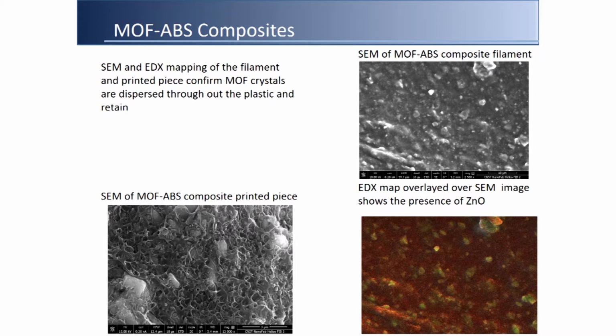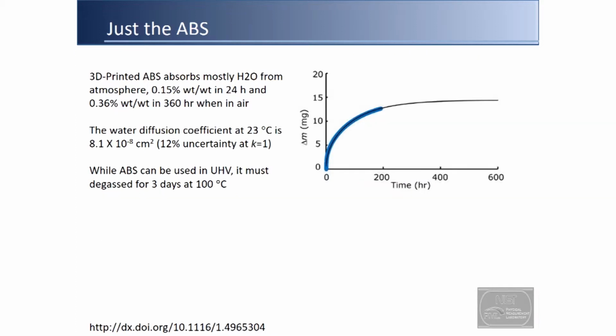If you look at the EDX map, those are zinc oxide. So these are real crystals, they have the zinc, so everything looks all fine. It should work. So let's look at the ABS itself, the native ABS. Well, it turns out it mostly likes to store water. In fact, a lot of water. And 360 hours after you bake it out, you can watch the water come on and on. Up to 0.36% by weight is just water.